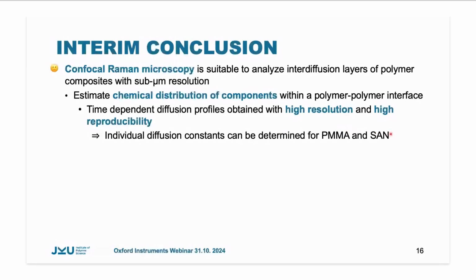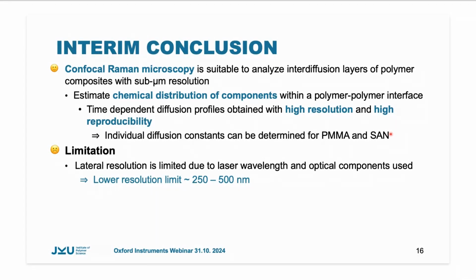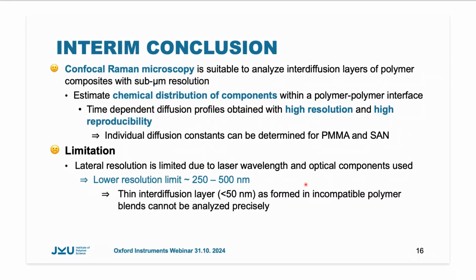But we are not sure if it's really the interdiffusion constant, because with all the techniques, we are not able to allocate the initial interface when we started. On the other hand, we have some limitations in confocal Raman microscopy. Here, the lateral resolution is limited due to the laser wavelength and optical components which we used. We found a lower resolution limit for very sharp boundaries in a range of 250 to 500 nanometers, which does not allow us to investigate very thin interdiffusion layers, as they are formed in incompatible polymers.